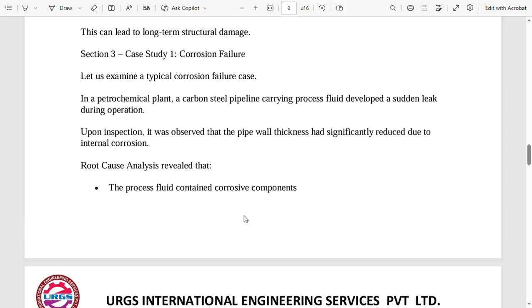Then section 3 is case study 1, corrosion failure. So let us examine a typical corrosion failure case. In a petrochemical plant, a carbon steel pipeline carrying process fluid developed a sudden leak during operation. Upon inspection, it was observed that the pipe wall thickness had significantly reduced due to internal corrosion.